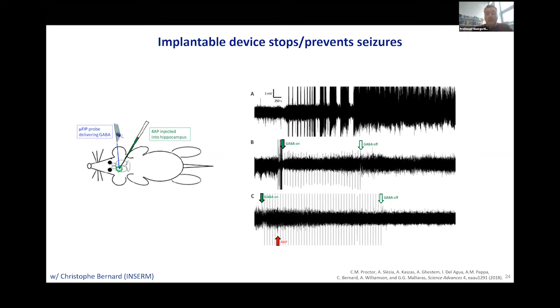So when validated in a preclinical model, this device shows quite efficient operation. So here are some data with the device implanted but turned off. Here we kindle a seizure, and then we wait a little bit and the seizure manifests itself. So the presence of the device switched off doesn't have any effect. Here, the seizure starts, and then we turn the device on, and you see that the seizure disappears immediately. These spikes that you see here are an electrical artifact that we pick up with our electrodes that corresponds to the puffing of GABA outside the device. So we apply pulses to send small puffs of GABA into the brain,